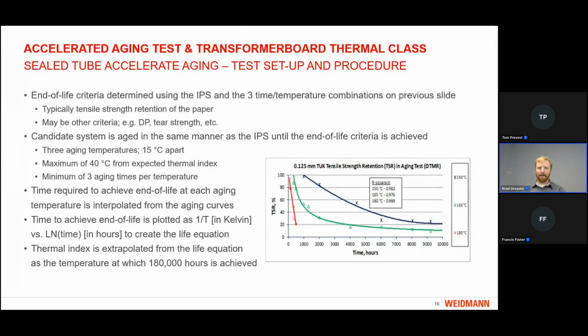And what you're trying to do by aging the candidate system at multiple periods is to build these aging curves shown in this graph on the right. So under the same aging temperature, as we have multiple aging vessels, we see the degradation in, in this case, tensile strength retention of our candidate system. After the end-of-life criteria is achieved, you interpolate on this line the actual time to reach the end-of-life criteria. So we have a line of best fit over the aging period, and at least one aging period must be exceeding the end-of-life criteria, and then by interpolating that line, we can determine how long it took to achieve that end of life.